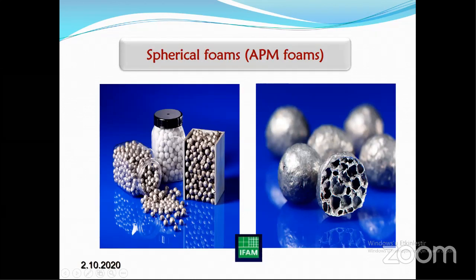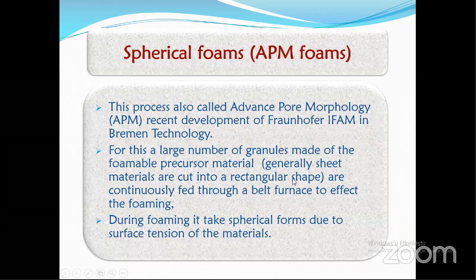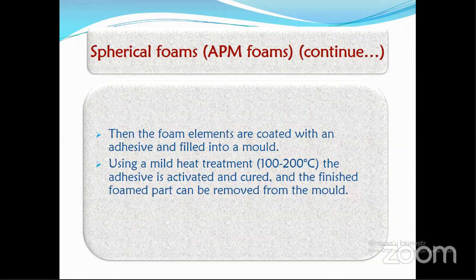Actually, spherical forms, now called advanced pore morphology, is a new one. This process, a recent development of Fraunhofer IFAM in Bremen, uses a large number of granules made of a foamable precursor material. Generally, sheet materials are cut into rectangular shape, and are continuously fed through a belt furnace to effect the foaming. During foaming, it takes spherical forms due to the surface tension of materials. Then the foam elements are coated with an adhesive and filled into a mold. Using a mild heat treatment, the adhesive is activated and cured, and then finished foam parts can be removed from